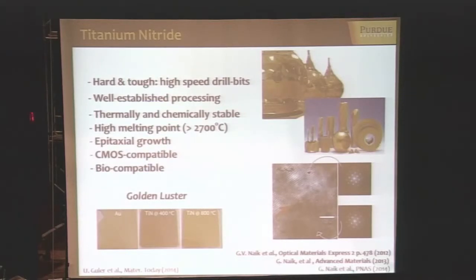It's used, for example, for high-speed drill bits. There is well-established processing—it's easy to make, and you don't have to create a new way to produce it. It's well known, and it is very refractory. The melting point for titanium nitride is 3 times higher than for gold, in bulk form. This also indicates that if you nanostructure titanium nitride, it would be able to sustain the elevated temperatures I was talking about.